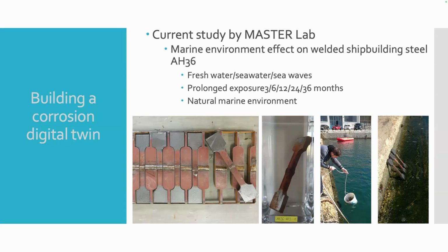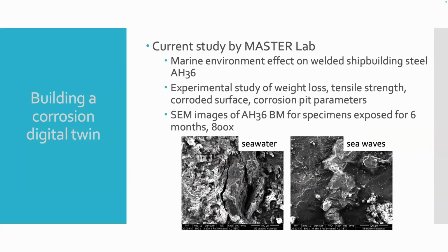And once we have extracted these specimens, we did weight loss measurements. We did the tensile strength testing. We inspected the corroded surface and accounted for corrosion pit parameters. You can see here, I have just put two pictures. You can find them also in the paper that we have published in the Engineering Failure Analysis journal.